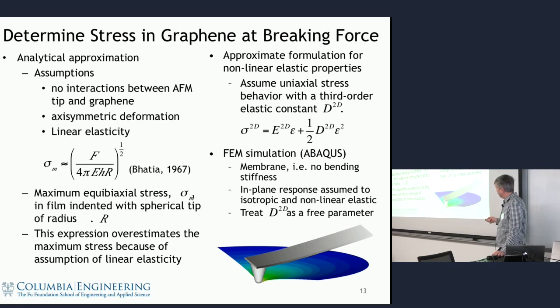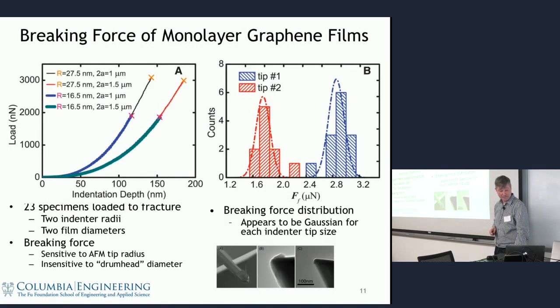On the other hand, all of our fracture mechanics is going to be right at the tip, and at this point we have no free edges. So we get rid of the edge problem. As long as we don't have defects in this center, we should see the intrinsic behavior of graphene rather than extrinsic behavior due to edges and clamping, things like that. All right, so what did we see? So that's kind of going backward.